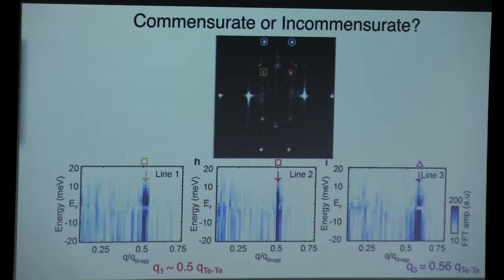The second thing is that these CDW peaks occur at incommensurate Q vectors. The direction is not in the direction of the Bragg peaks. That tells you that it's incommensurate.